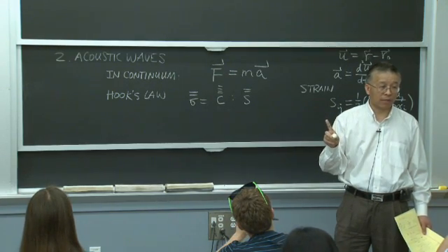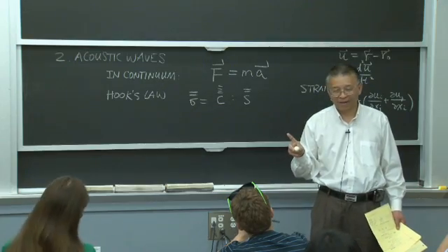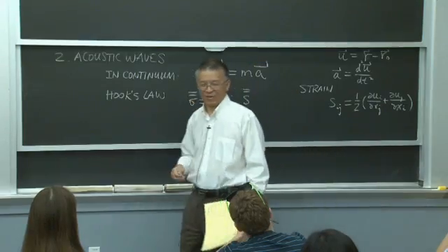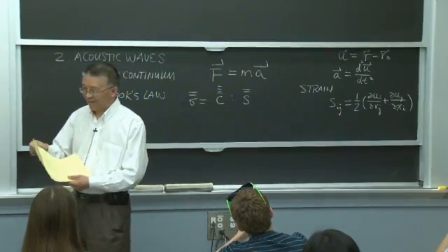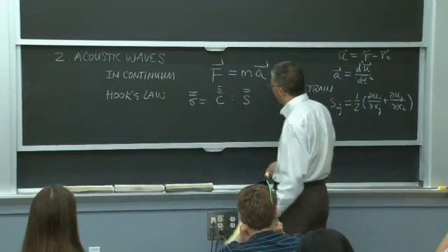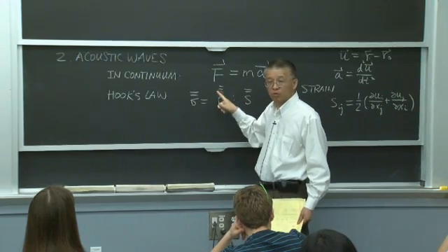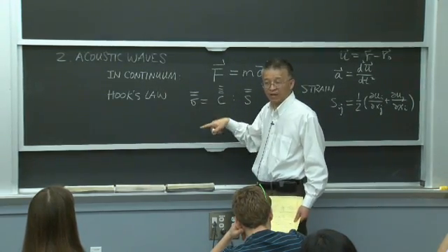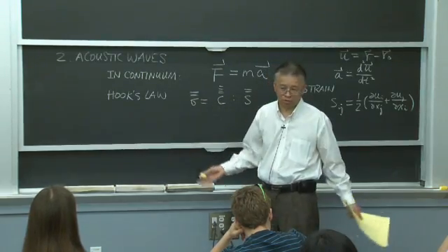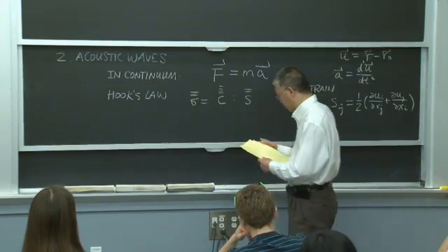Each order is 3 components. Second order tensor has 9 components. Fourth order tensor has 81 components. Okay, so anybody doing solid mechanics must be very good at the math. That's a lot of tensor operation. Due to symmetry, you can simplify 81 to 36. And if you have an isotropic material, you get only 2. So those are the different assumptions made.